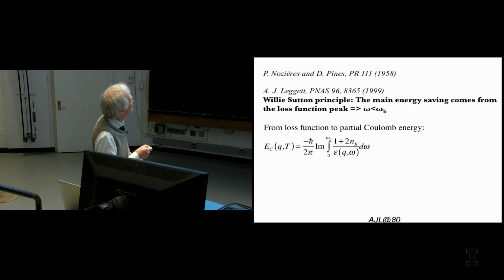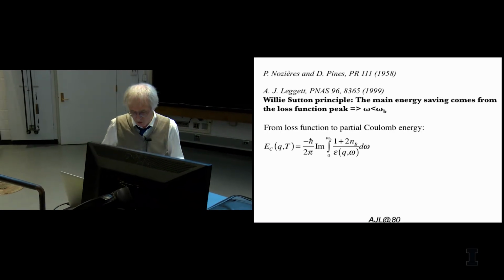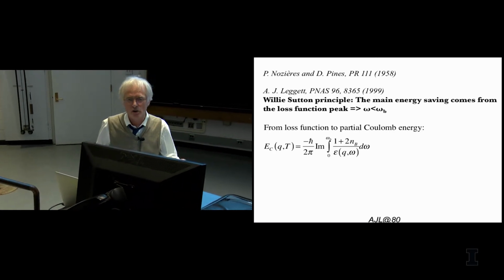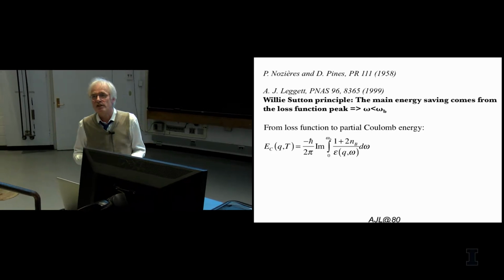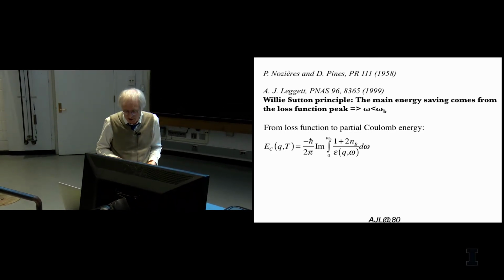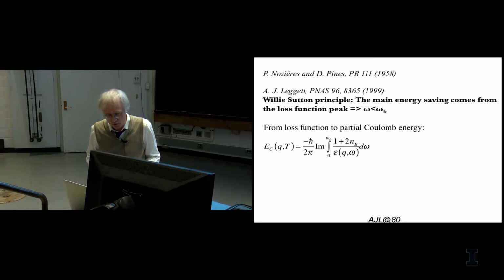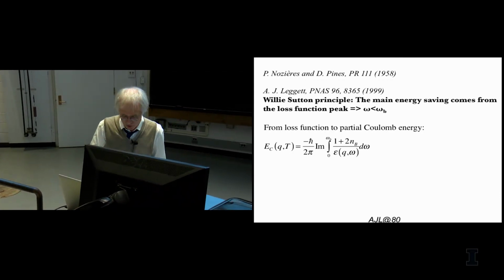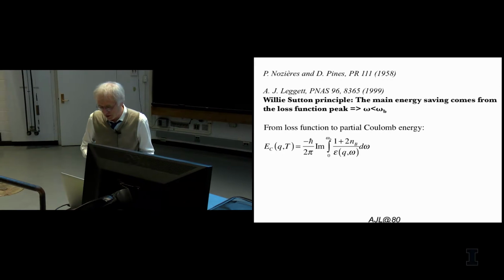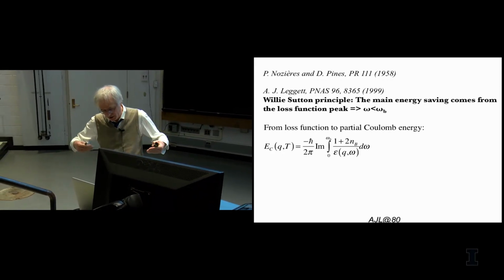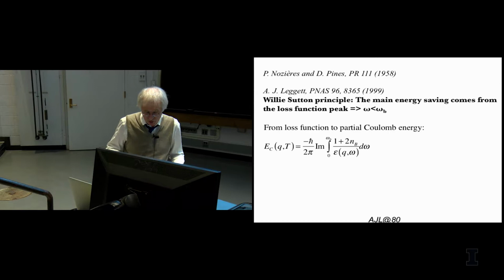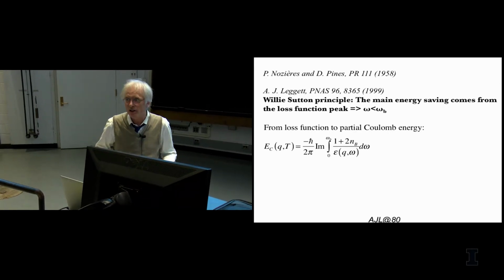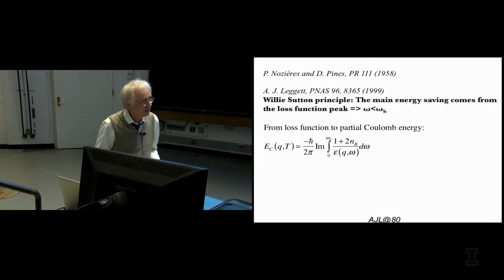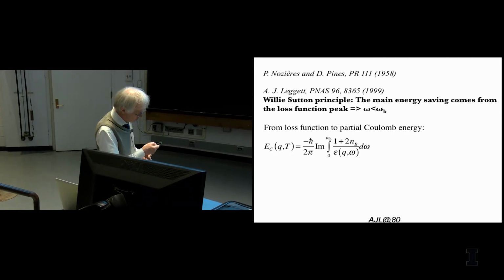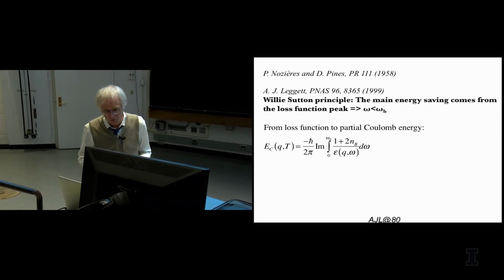So the main energy saving has to come from the loss function peak around 1 electron volt, and also where the peak is strongest, and we saw it is strongest for small momentum. The reason is that there is most of the spectral weight anyways, and so if anything changes, this would have the biggest influence. There's a much more subtle and microscopic reasoning behind it, which essentially means that the main saving of Coulomb energy is caused by the system changing its screening, where you go from normal to superconducting, and that's profiting mostly from that part of which we saw the spectra just now.